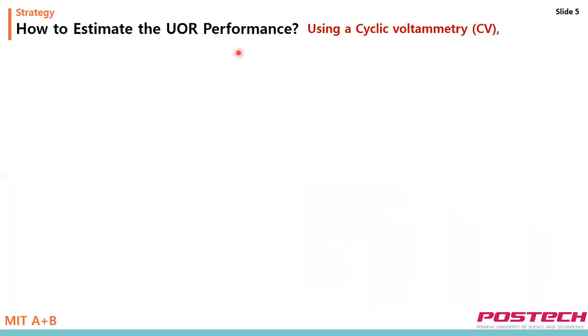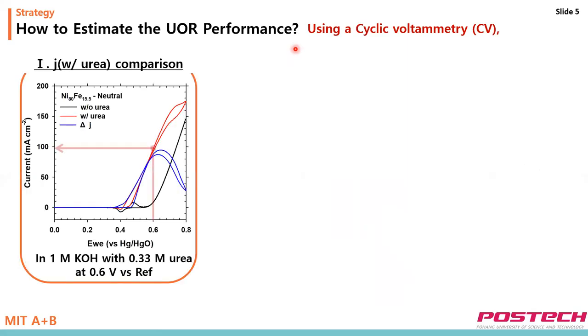Then how should we evaluate the UOR performance using activated alloys? First, look at the cyclic voltammetry graph as an electrochemical analysis. The current response in the absence and presence of urea in the solution. With the addition of urea in the solution, the current is considerably increased. This current difference can be attributed to UOR.